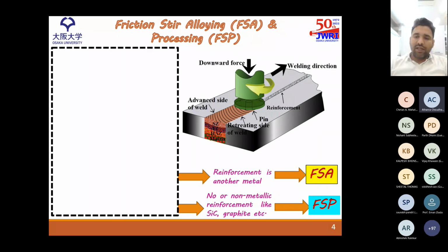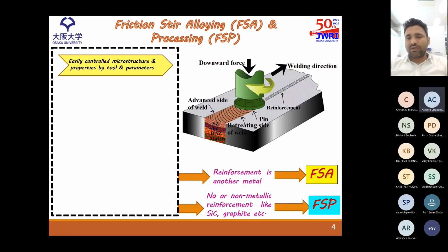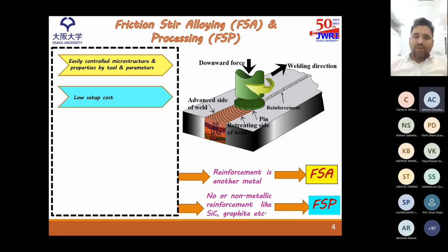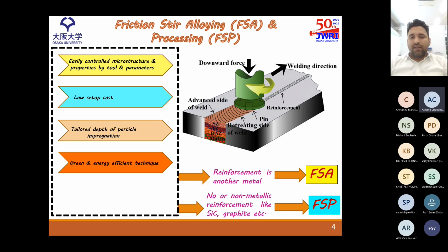Now, why are we conducting this processing in a solid state when we can do it by casting? Because of certain advantages of this process. The microstructure can be easily controlled. Whatever we are producing, we are producing it in a solid state, so the material properties remain intact. The overall setup cost is very low. It can be done on a milling machine, and the particle impregnation depth can be easily controlled by the tool pin.